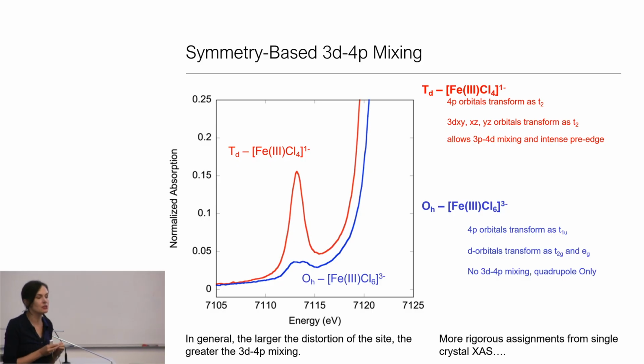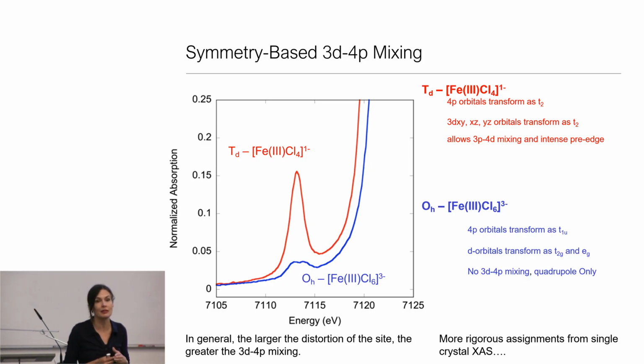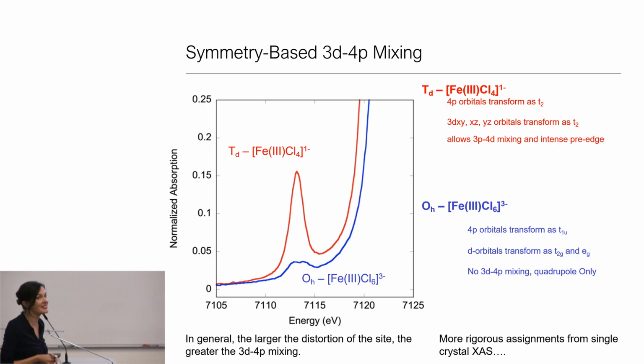That said, the pre-edges, which tend to be intrinsically weak because in a centrosymmetric limit they are only quadrupole allowed, these are incredibly informative. And so we talked about in the group theory talk that I was going to use octahedral and tetrahedral examples a lot. The reason that I'm using this is, of course, in the octahedral limit, if we were to go to our Oh group theory character table, we would go back to seeing what we already saw on Monday, that our d orbitals transform as T2g and Eg, but our 4p orbitals transform as T1u. And so there's no mechanism to get any p character into this pre-edge. Hence, this pre-edge is weak, and it reflects only a pure 1s to 3d quadrupole transition in rigorously octahedral symmetry.